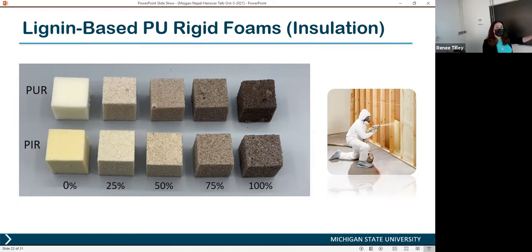There were some publications where they modified lignin, broke down lignin to a smaller chain, or did oxypropylation. That is, they used chemicals, toxic materials to do that, but this is unmodified solid lignin up to 100% of the petroleum-based polyol, which is 30% of the total weight of the foam, replaced with lignin, and that's again used for insulation application.